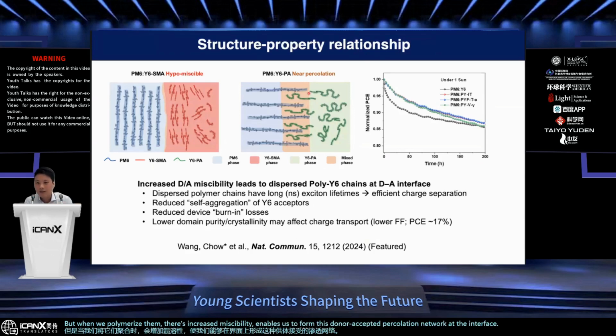So this structure actually serves two purposes. The first is that, remember, when we disperse the polymer chains, the exciton lifetime is greatly enhanced. So this firstly satisfies the condition for the efficient and slow charge separation, enabling the electrons to gradually separate upon thermal activation at the interface.